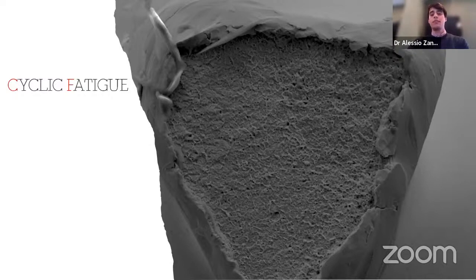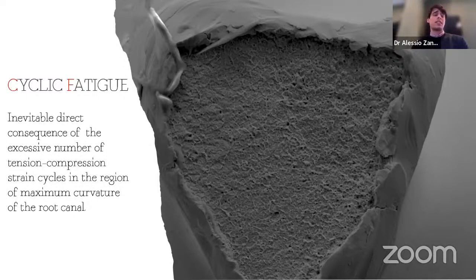Those are some micrographs acquired by the scanning electron microscope. We see the fragment of an instrument arising from cyclic fatigue failure. Cyclic fatigue is an inevitable direct consequence of the rotation of the instruments in the root canal curvature. They are subjected to strain cycles of tension and compression. Once the elastic limit of our instruments is overloaded, we have plastic deformation and then fracture. This is the fractographic pattern. As you can see, the fracture starts from the external surface of the instrument and propagates toward the center, causing a ductile fracture.